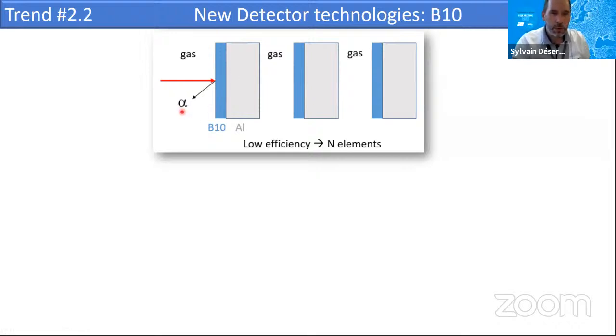Now, as a scientist, you should know that alpha particles can be stopped very easily. This is why this coating needs to be very thin, on the order of 1 micrometer. This thin coating also means that the probability of absorption of the neutrons in the coating is weak, so there is a low efficiency. This is the reason why this setup has to be reproduced n times in series, so that at the end the efficiency meets the requirements.